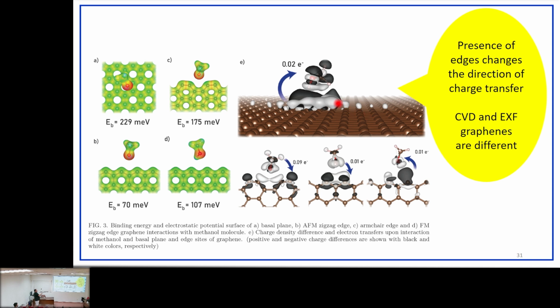You see, if you have CVD graphene, and there is an approaching methanol molecule, then there is a charge donation from graphene to methanol. And for edges, you see, if you have an armchair edge, and there is an approaching methanol molecule, there is a charge donation from methanol to the edge. It's different. It's vice versa. And for zigzag edges, you see, for one of them we have charge donation from methanol, and for the other one from the edge to methanol.